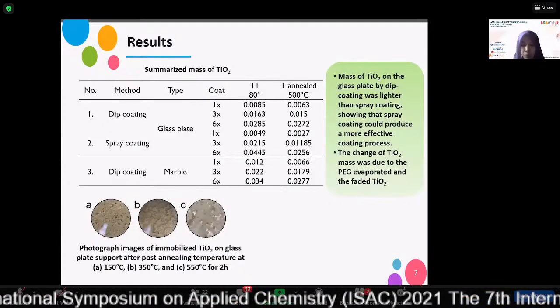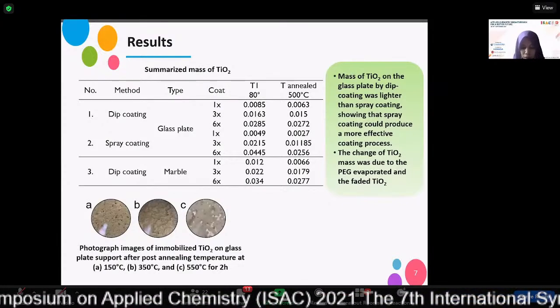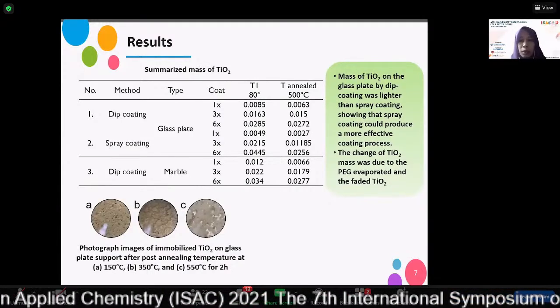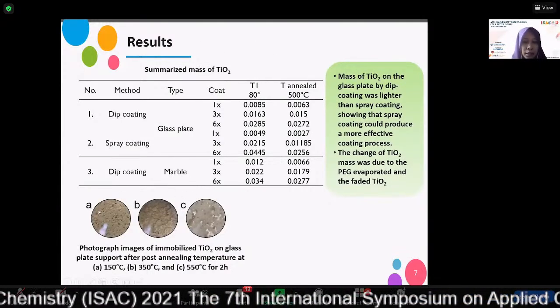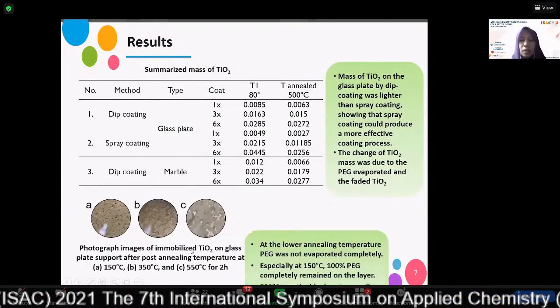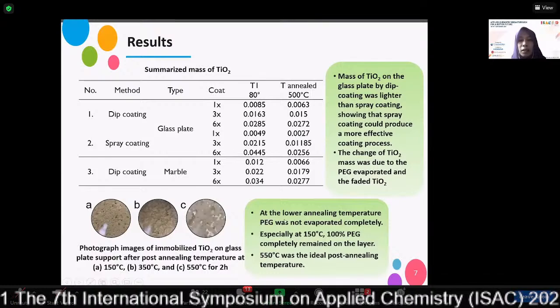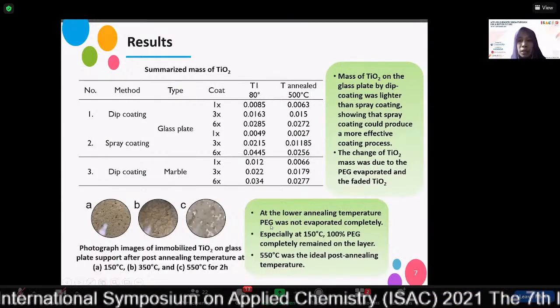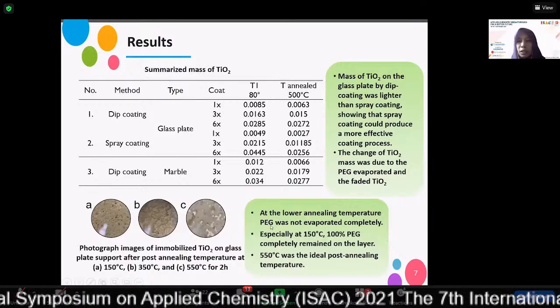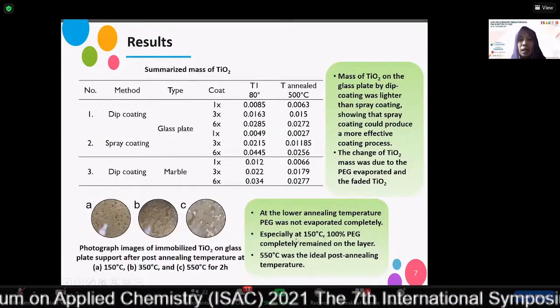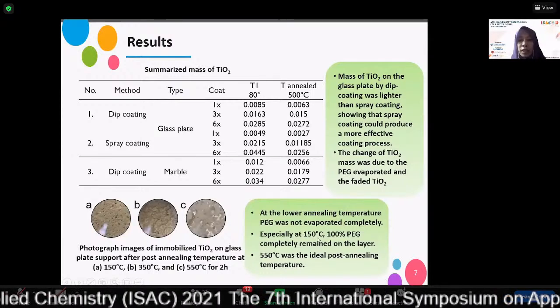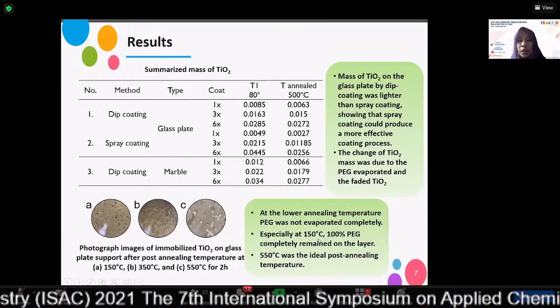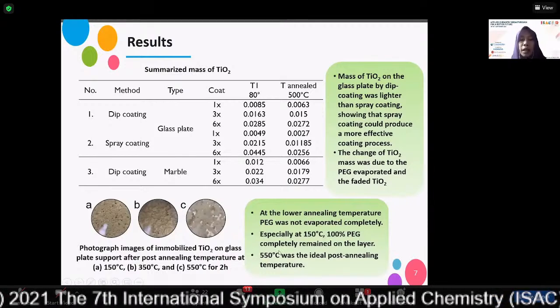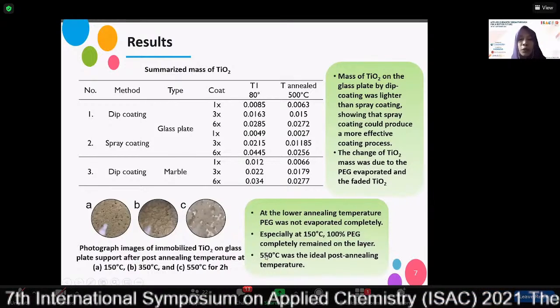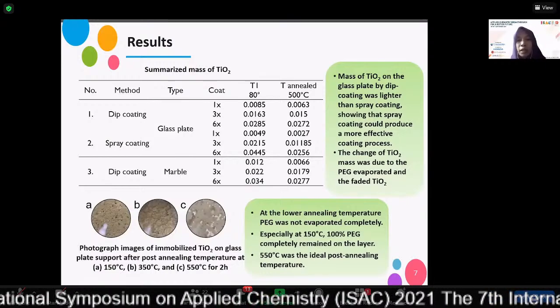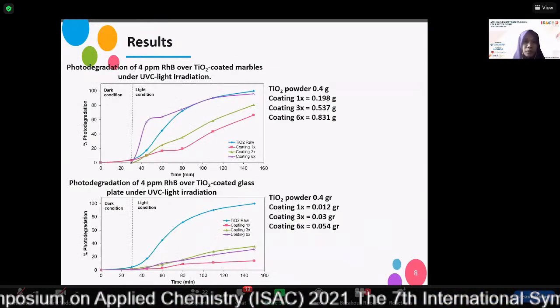The effect of various temperatures of the post-annealing process was studied, and the result is this picture. It showed that at the lower annealing temperature, PEG was not evaporated completely, especially at 150 Celsius. At 150, PEG completely remained on the layer, and 550 degrees Celsius was the ideal post-annealing temperature.